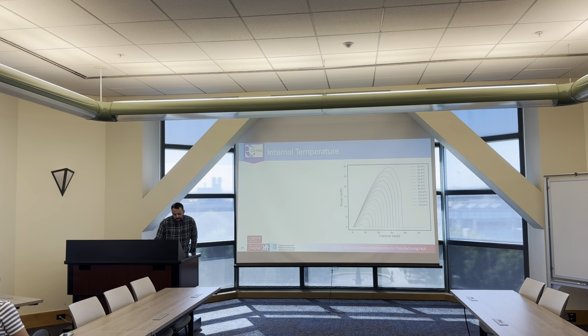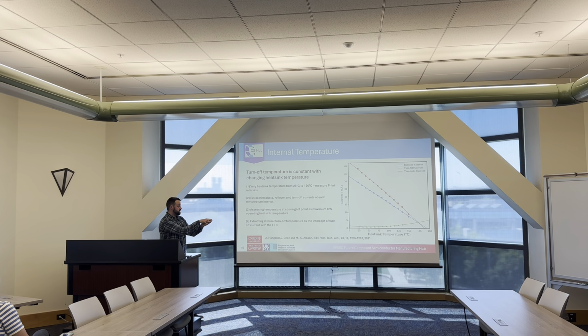So measure lots of LIVs as a function of heatsink temperature. So from 25 to 150 degrees Celsius here, and then extract the threshold current, rollover current, and turn-off current at each of the temperature intervals. Then these converge at a certain heat sink temperature, and that's the temperature corresponding to the maximum CW heat sink temperature. But then, if we extrapolate the red curve, the turn-off current, down to zero, then this represents the average cavity temperature at turn-off. So that's what I'm going to compare between the devices.